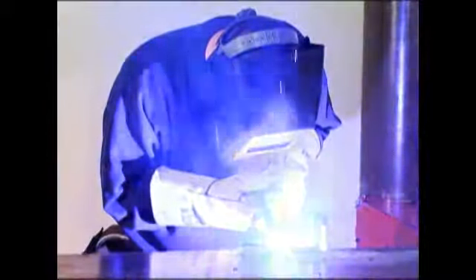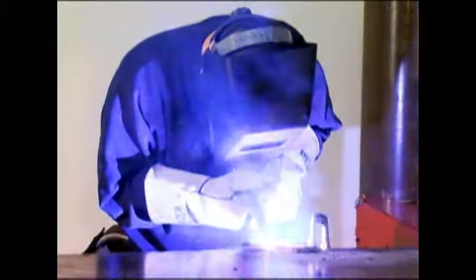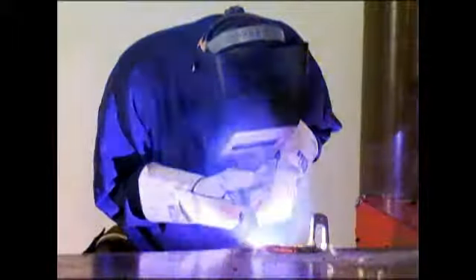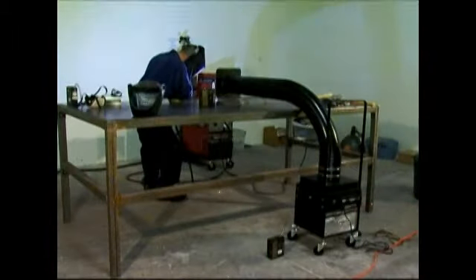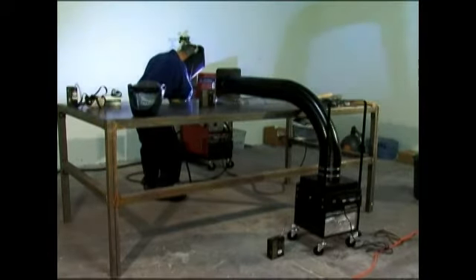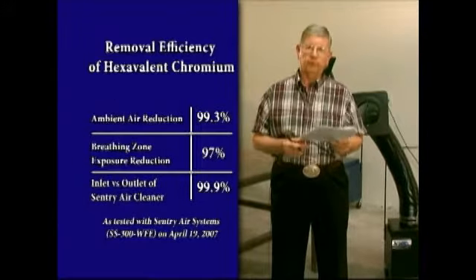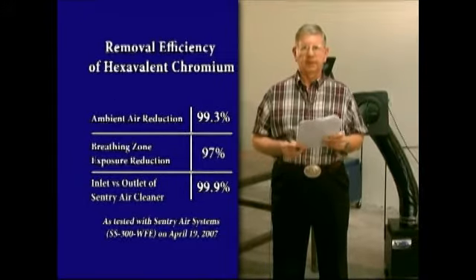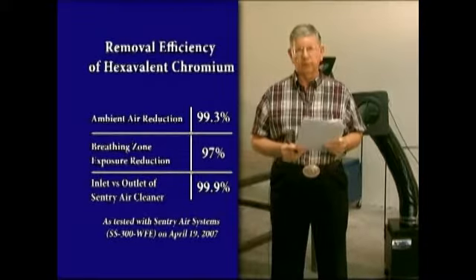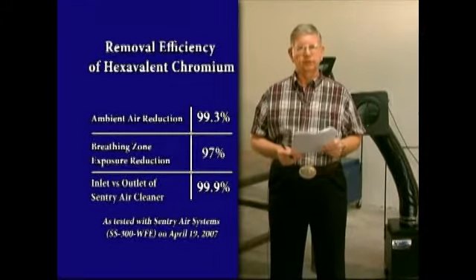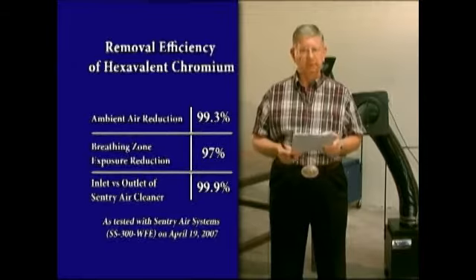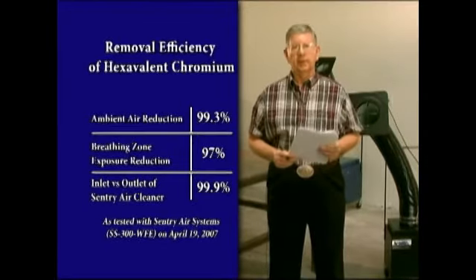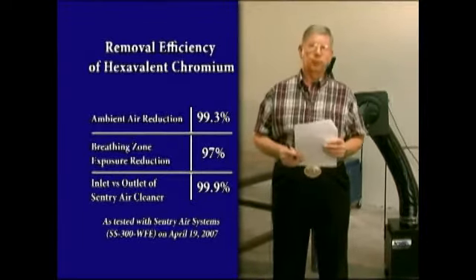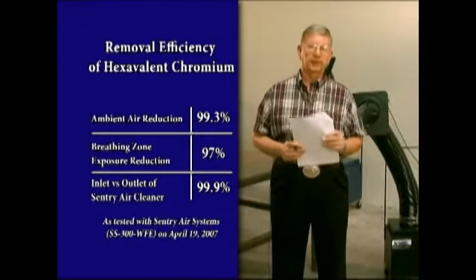We did 4 hours of sampling in the morning without the machine operating. And then we compared those results with 4 hours of sampling with the machine operating in the afternoon. And we saw the ambient air showed a 99.3% reduction in hexavalent chrome. The welder showed a 97% reduction in his breathing zone concentrations of hexavalent chrome, and the machine itself showed 99.9% removal from inlet to outlet.